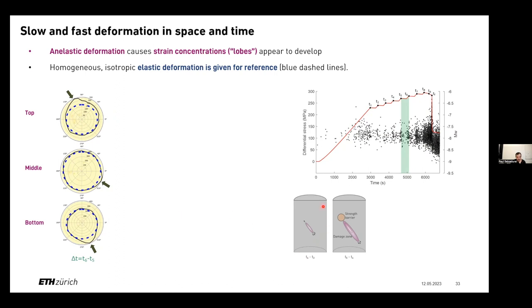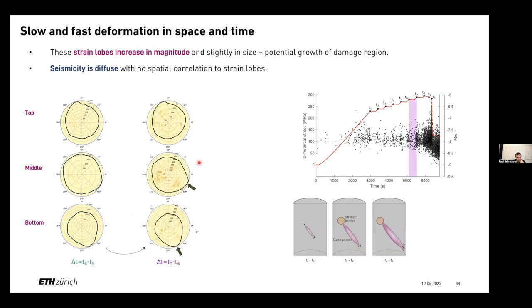And what we have here is a schematic diagram of what we think is happening within the sample. We feel that when we map these, and there's more research we're doing into mapping this damage zone better, as we move up there's still diffuse seismicity. There's no localization in seismicity, but the lobes are growing, meaning there's some kind of internal process that's not generating seismicity above our detection level. But it is occurring on a large scale, and quite a significant degree of deformation is occurring. So these lobes are increasing without the generation of a lot of seismicity.